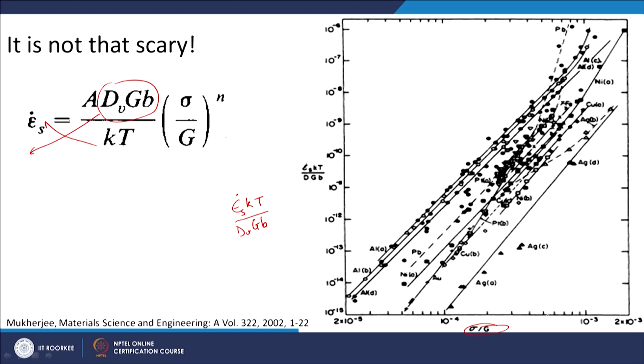Of course it is also on a logarithmic scale, you can see, because you have to take log on both sides to make it linear, okay. Again the same idea we are using. So if you take log on both sides, the n will come as a slope, okay. So instead of taking log, actually if you see, they have plotted on a log scale, okay. You can see 10 to the power minus 5, 10 to the power minus 4, 10 to the power minus 3. Okay, this is my log scale. Similarly, this is my log scale, 10 to the power minus 14, minus 13, minus 12 and so on. So instead of taking log here, they have made the scale logarithmic. Okay, that is why you do not see log on the parameter here.